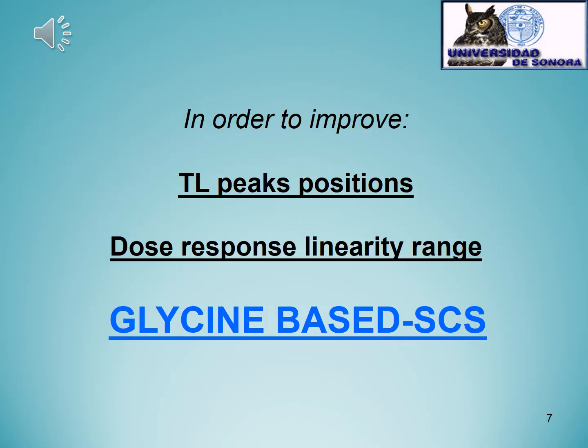In the work mentioned before, all the phosphors synthesized by solution combustion synthesis were obtained using urea as fuel. In order to improve TL peak positions and dose response linearity range, we proposed changing the fuel from urea to glycine, making a glycine-based SCS process.